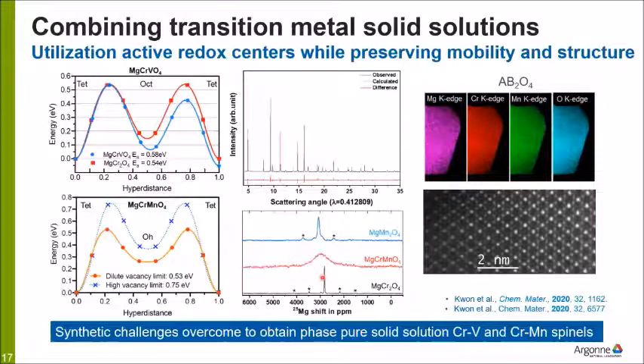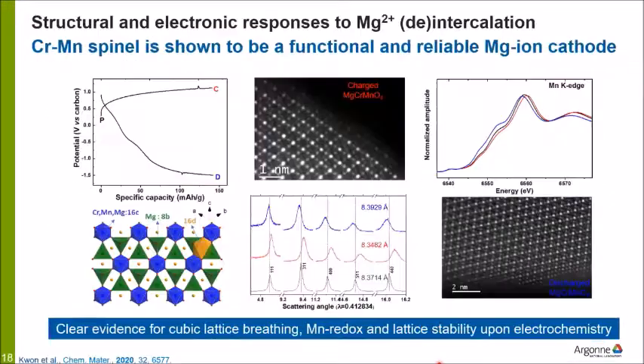And here you can see NMR analyses of the pristine material. So once again, here's the magnesium peak. It's nice and sharp in the chromite. It's fairly sharp in the manganese state. And you see this broad distribution, which is indicative of a varying environment that the magnesium observes between a mixed manganese and chromium state. The synthetic challenges to obtain these as phase pure materials were overcome, and you can see that we have fairly nice phase pure solid solutions of these materials.